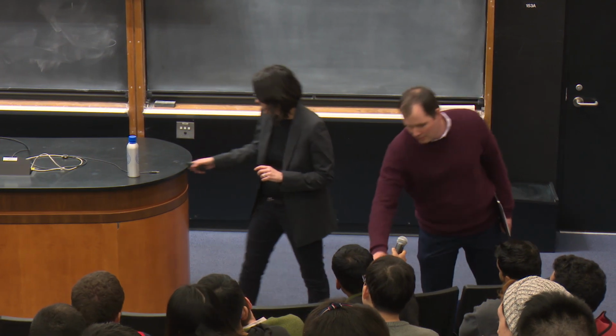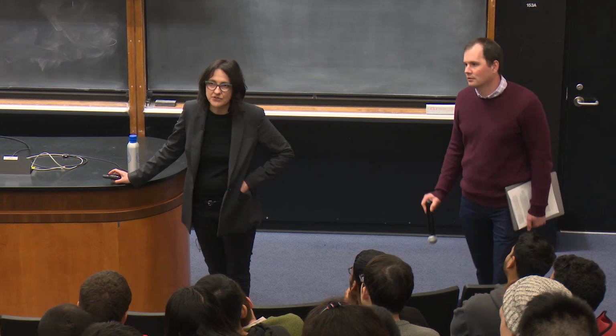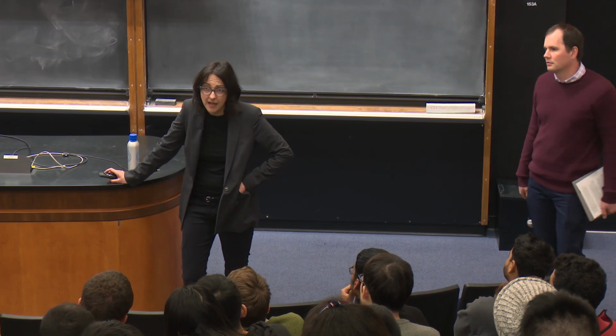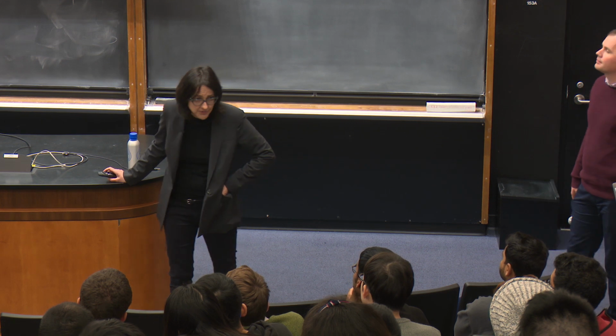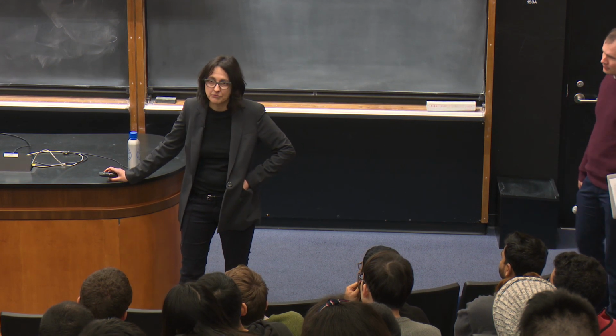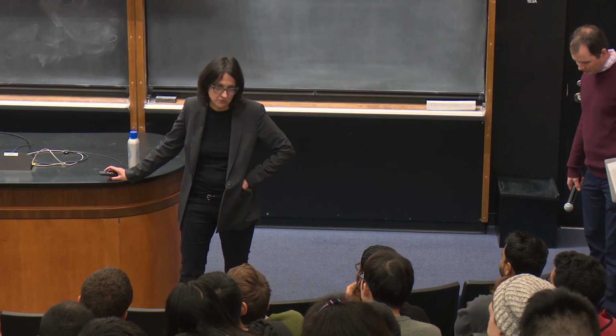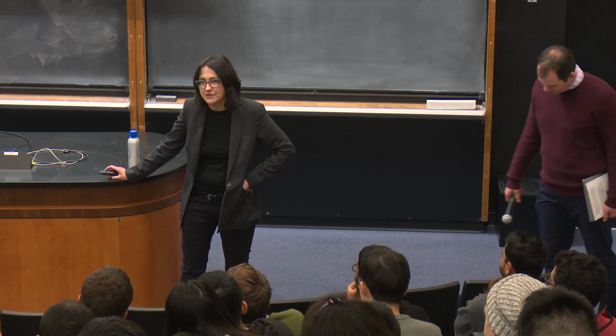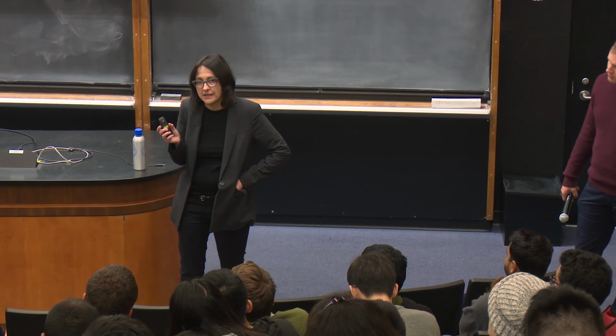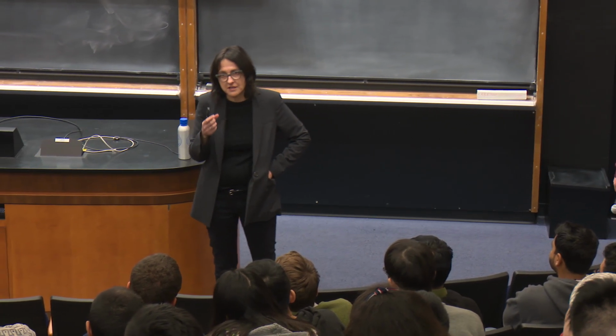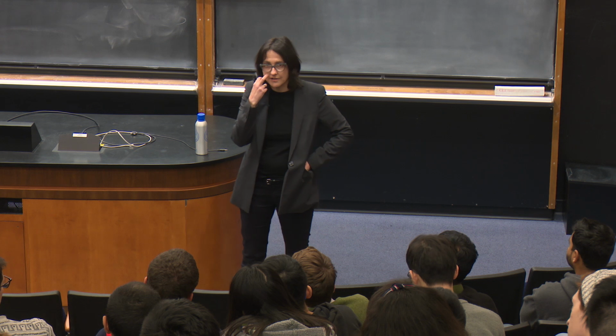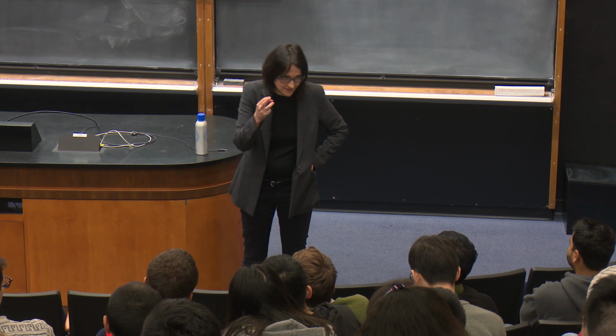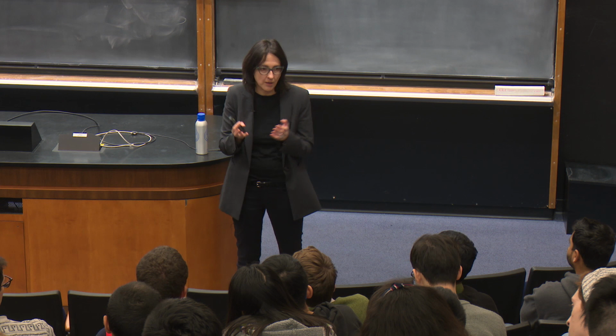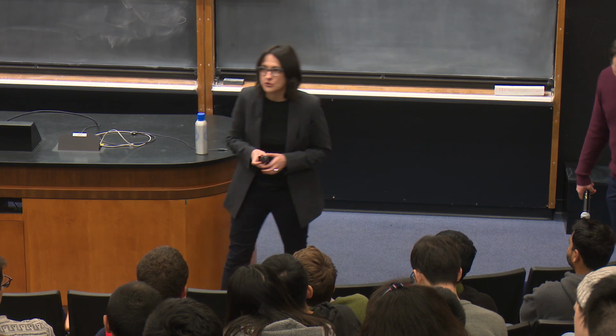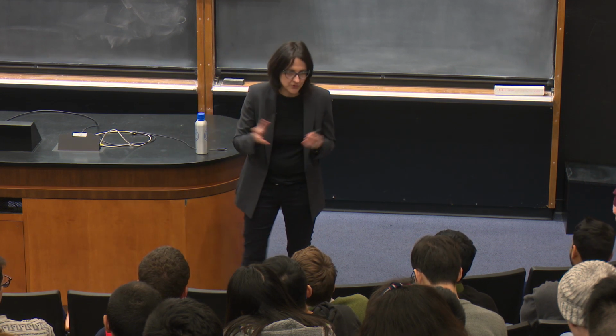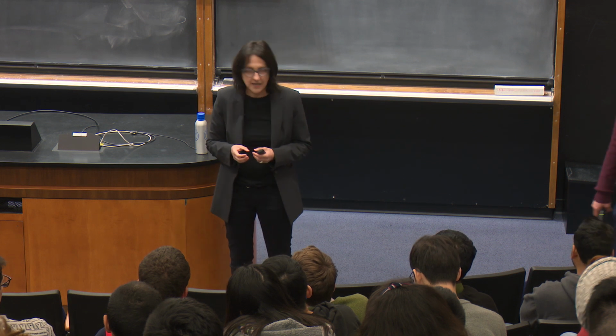Yeah, that's an excellent question. And we've done some work on that. So it's the energy landscape for the cost function. We've analyzed it for certain problems. We were curious about it. We did it for the problem of the wavelength splitter and also the mode converter. First, even in such a constrained footprint, for greater than 90% efficiency, we can find more than 6 clusters of solutions with greater than 90% efficiency, right? So these are all local optima, and this is local optimization, right? So you can converge to one of those local optima, and of course there are some other lower efficiency solutions around that.